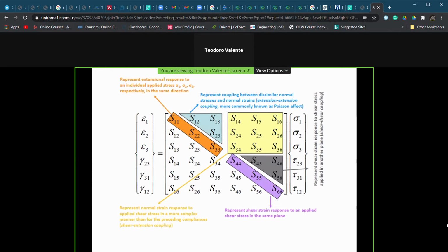The general meaning of the terms of this S matrix is what is reported on this slide. So these terms S11, S22, and S33 represent the extensional response, because we have epsilon here, to an individual applied stress along the direction 1, 2, 3, respectively. S44, S55, S66 represent the shear strain response, since here we do have the shear deformation, to an applied shear stress in the same plane.